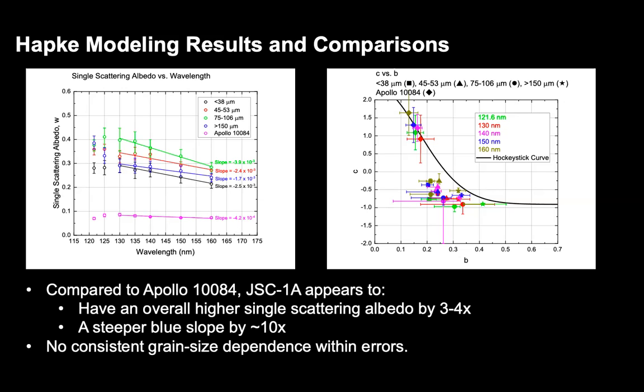We have our ideas. A lot of it probably does stem from the space weathering characteristics. In case of the overall brightness, the overall increase in single scattering albedo, that's probably due to the space weathering, because the nanophase iron is a darkening agent. So that is probably due to the nanophase iron itself. But the difference in blue slope, that's interesting. And that's one we're really going to have to think about as to what the reasons are for that.